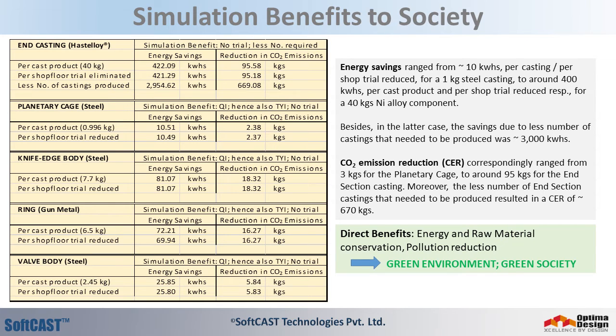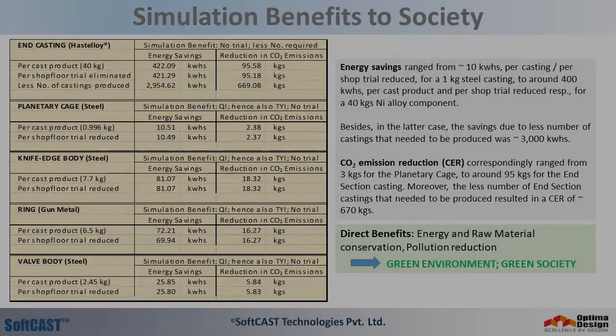Pollution reduction, as measured by reduction in carbon emission, ranged from 3 kilograms to 95 kilograms per casting correspondingly. Further, in the case of the end-section casting, the less number of buffer castings that needed to be produced contributed to a CER reduction of about 670 kilograms. All this contributed to a green environment and green society.